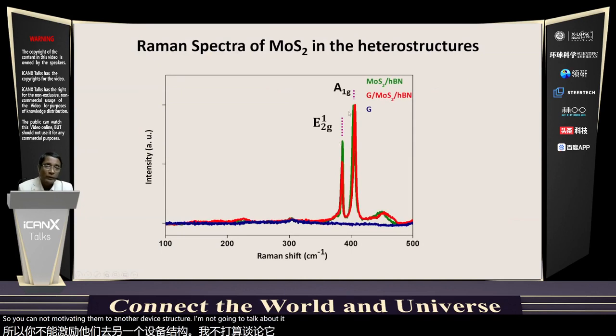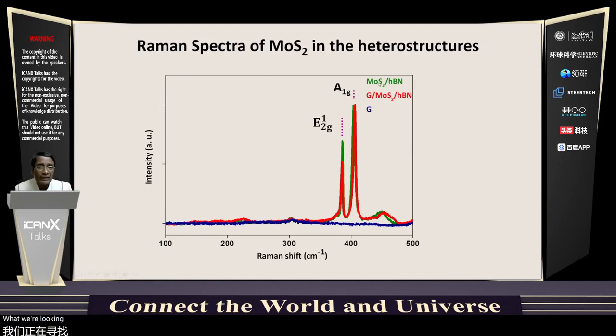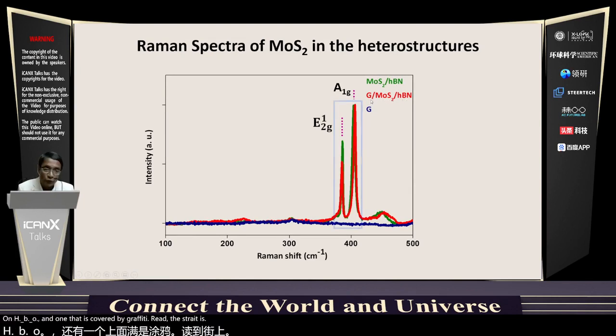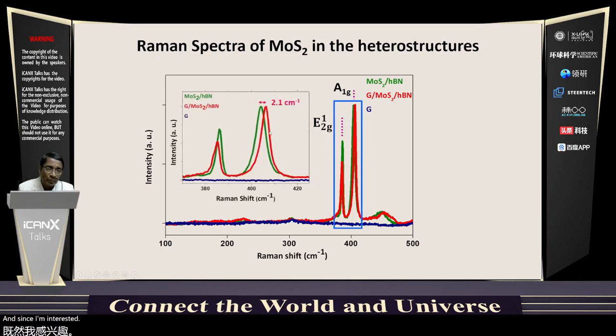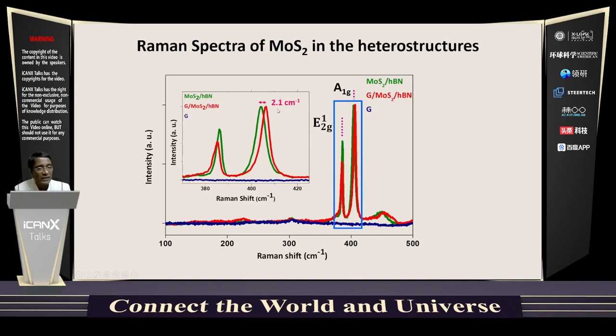This is the molybdenum disulfide Raman spectrum, because that can sensitively measure the strain. What we're looking at is molybdenum disulfide on HBN and one that is covered by graphene, where the strain is supposed to develop. And since I'm interested in this part, if I pull it out, I see that there is indeed a shift in the phonon frequency of 2.1 centimeter inverse, and that translates into a composite strain of 1.2%. Knowing that my system is strained, we now look at the electronic properties by looking at the photoelectron spectroscopy.